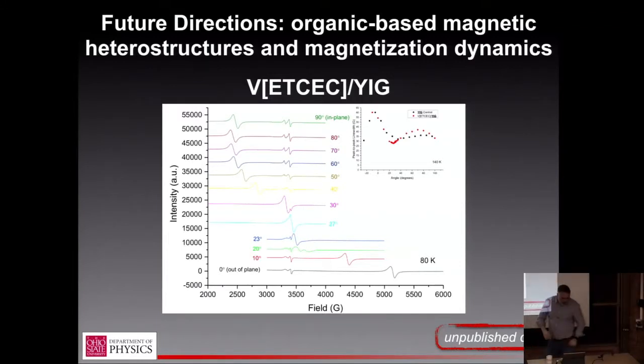And I'll say for this technique, the problem is this. The clever thing I thought I was trying to do with using the VTCE is the low Curie temperature means we can measure above and below the Curie temperature. So we actually have done this with VTCE as well, but it's not easy to turn it off. We didn't have a good control measurement. So here we were thinking, oh, we can vary the temperature. And what we failed to take into account, these black dots here are the line width as a function of angle for just bare YIG. And it's actually quite a complicated line shape. That slowed us down a little bit, that there's response in the YIG that makes it not so easy to interpret the line width. We're working on it, and we think that we may be able to, but we haven't been able to yet.